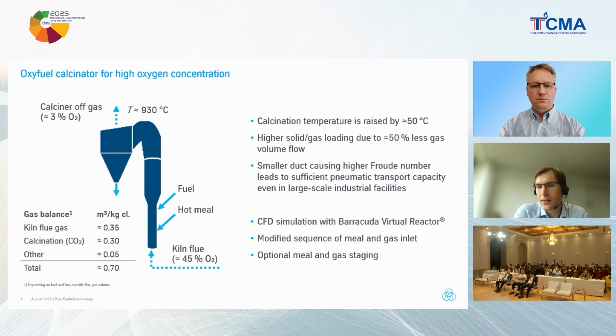In the development phase, this also has been intensively investigated by the Barracuda Virtual Reactor CFD package, which is capable of simulating entrained flow reactions. There's also the principle to first add some hot meal and after that the fuel into the calciner, because ignition is no longer an issue, but it shall be ensured that there is some hot meal, some calcium carbonate in the gas stream to absorb the heat from the combustion as soon as that takes place.